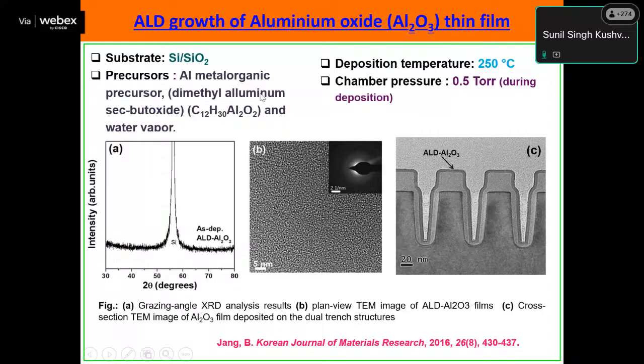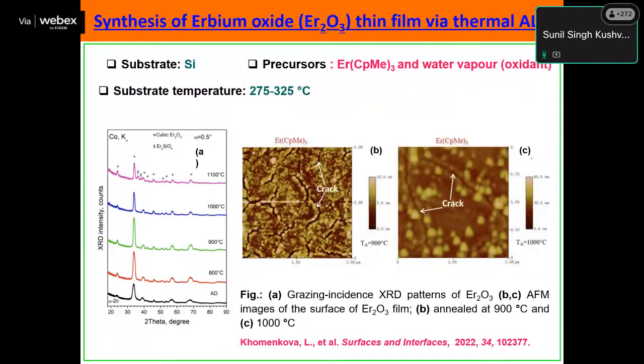As I mentioned, you have to select the precursor from a lot of precursors. For example, for aluminum oxide, it is an aluminum metal organic precursor, then dimethyl aluminum butoxide, and then some water vapor, and then you have to follow some deposition pressure and temperature, depending on whether it is thermal ALD or plasma enhanced ALD. This is one example of making Er2O3. Here again you have different precursors. Then people have used AFM and XRD to see the effect of temperature, or after the growth they have annealed at different temperatures. So this is a process by which you can grow the film, and especially for oxides, you can anneal at high temperature, and from that you have control over the quality of the film.